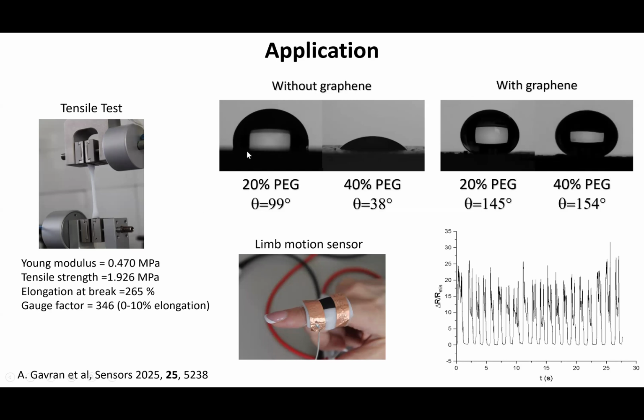Again, this is super hydrophobic. Without the graphene on top, you see that a drop of water will just spread on the surface. With the graphene, you get this really nice sphere of water just standing. This is useful for applications because it's sweat repellent as well.